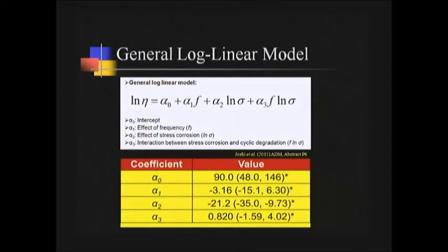And with the second term, he sees that the 95% confidence interval does not overlap with 0. It's negative, all in the negative range. And so that tells us the second term, which is related to the overstress condition, has an inverse relationship between stress and lifetime. That's what the negative coefficient indicates. So that's what we expected.